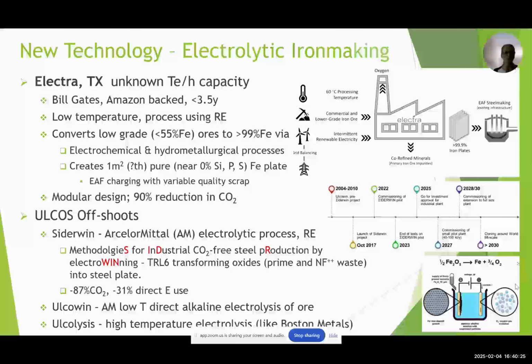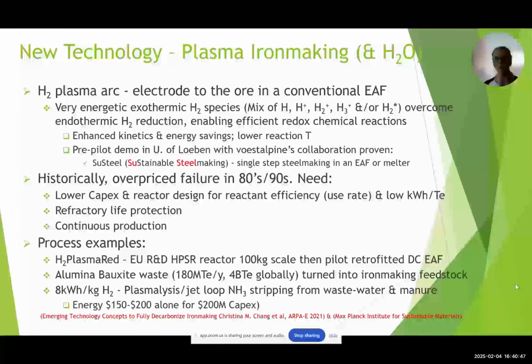There's also some ULCOS offshoots: Siderwin with ArcelorMittal, I mentioned, Ulcowin, which is another ArcelorMittal low temperature alkaline electrolysis, and Ulcolysis, which is basically equivalent to our friends Boston Metal. Plasma iron making is electrode to ore plasma in a conventional furnace with very energetic exothermic hydrogen species which overcome the endothermic hydrogen reactions, enabling efficient redox chemical reactions. Enhanced kinetics, lower temperatures, and there's a pre-pilot demo in the University of Loeben with voestalpine called SuSteel.